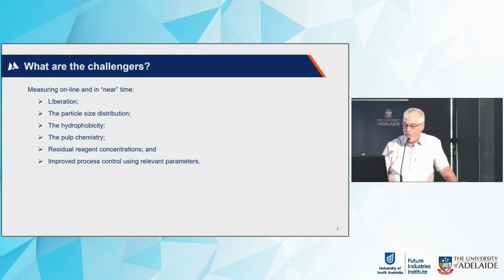So, what are the challenges? The challenges, as I see them, are to be able to measure liberation. Now, I'm not talking about grinding 100 million tonnes of ore to a P80 of 38 microns, because primary grinding is about liberating the non-sulphide gangue from the sulphides. Regrinding is about liberating the valuable sulphide from the gangue sulphides. So if you could measure liberation, particularly around regrind, you could actually monitor what you should grind to and reduce your energy consumption and be more specific on what you're trying to do in regrinding.